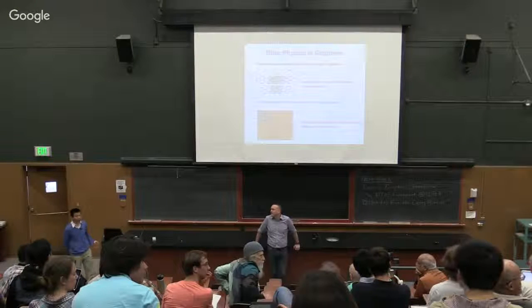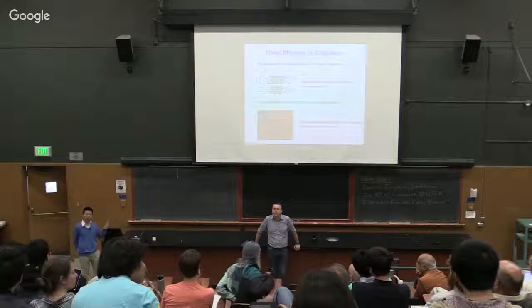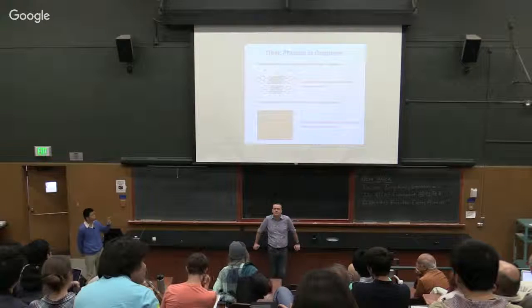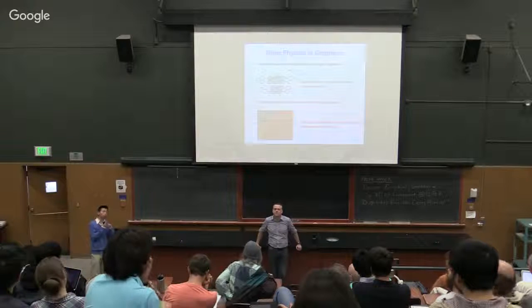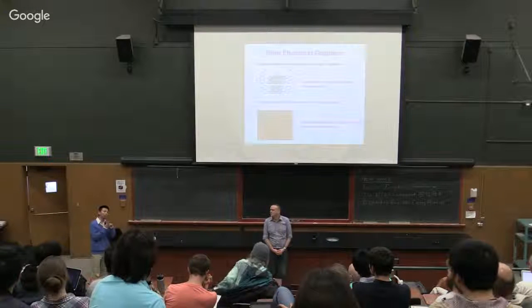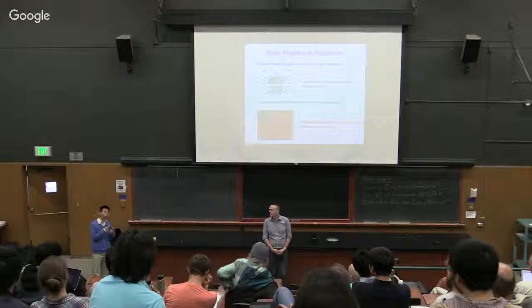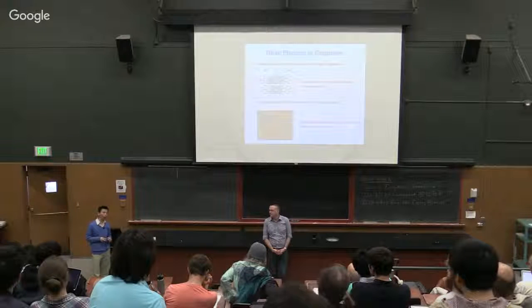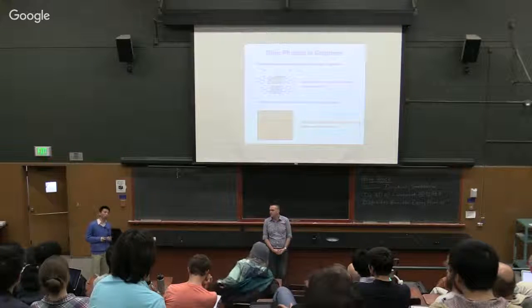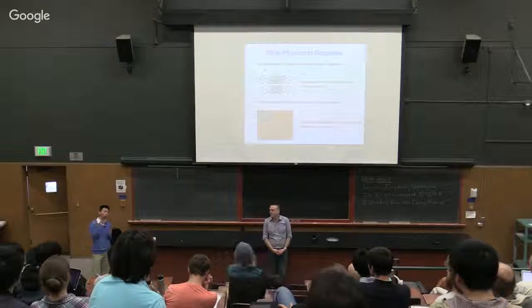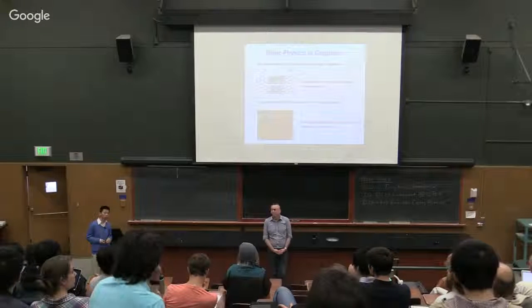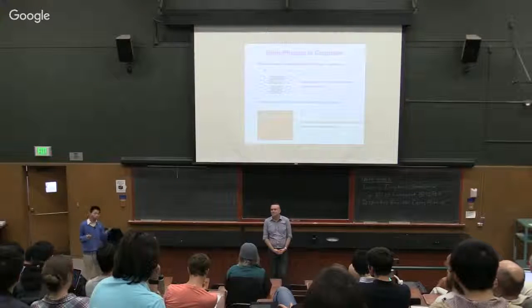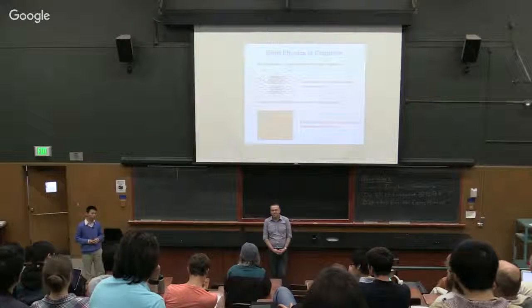So that's very interesting. For this one-dimensional nanotube with Dirac electrons, the dispersion of the plasmon is strictly linear. So basically, the velocity is constant. For all the plasmons, no matter what energy, the velocity is constant. That's very different from the 2D case or the 3-dimensional case.